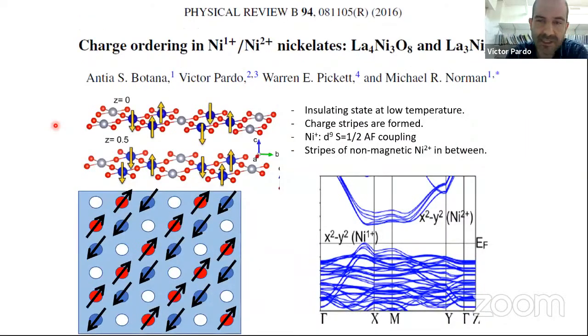So we said, okay, let's try to calculate some supercells. And what we saw is that there was a particular charge order pattern that was the ground state, that was lowest in energy. And it goes something like this, as you see in this cartoon. Some stripes are formed at low temperature that have nickel 1 plus, which are spin a half, and a stripe of nickel 2 plus.